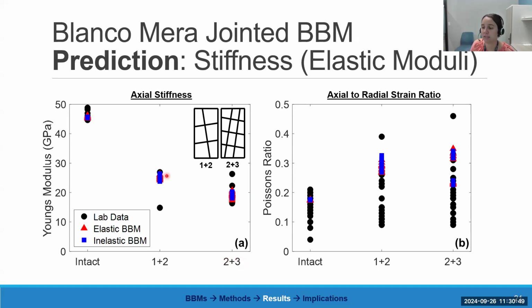So you'll see for both cases, the elastic and the inelastic block BBMs were able to predict the Young's modulus values within the approximate middle of the range of laboratory data for both geometry cases. And this was the same for Poisson's ratio here on the right. Of course, we have a much larger spread of Poisson's ratio values, which is typical for Poisson's, as most of you probably know. But again, this calibration was able to yield these two predictions, which fall within the approximate middle of the range of the lab data.